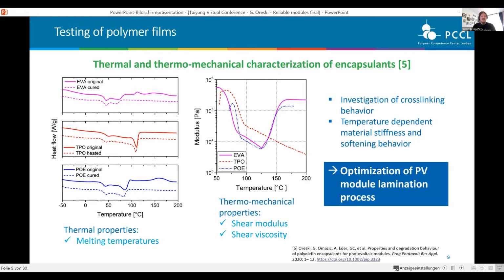And actually, you can use this method to optimize your process. Looking at these thermal properties, cross-linking starts around 120 degrees. So that's the temperature we need in the sample. From DMA, you see softening starts at 80 degrees Celsius. So you shouldn't apply the vacuum before that, because then the material is much stiffer and you may introduce stresses. So this is quite handy and useful.